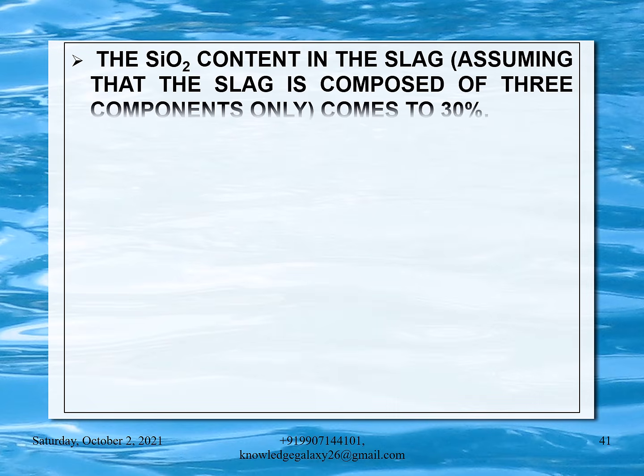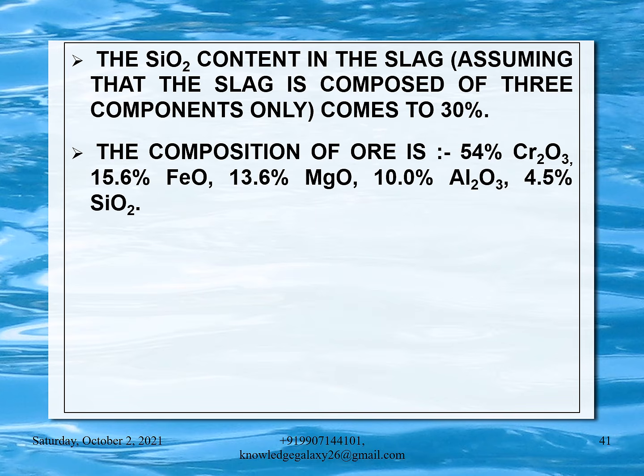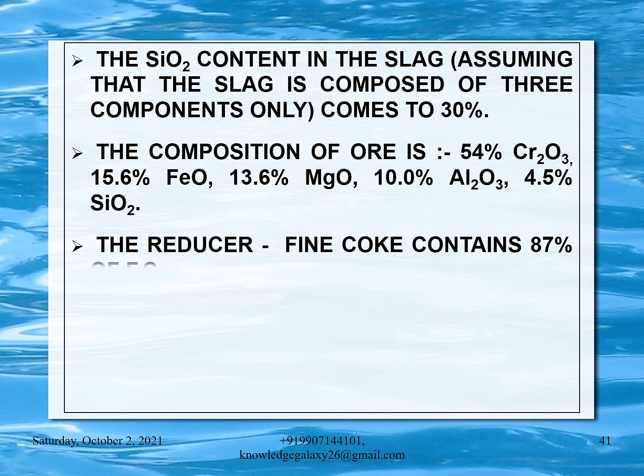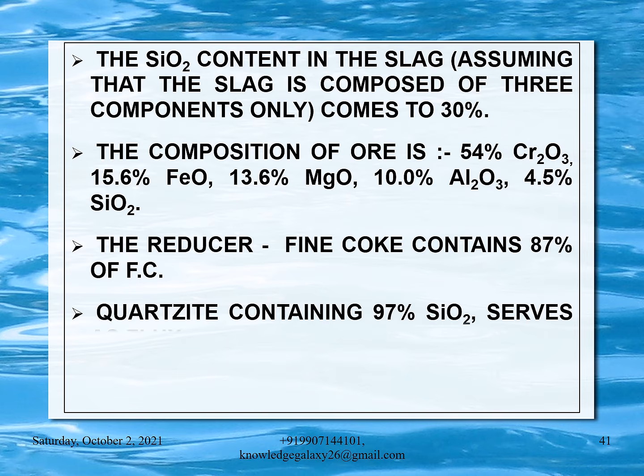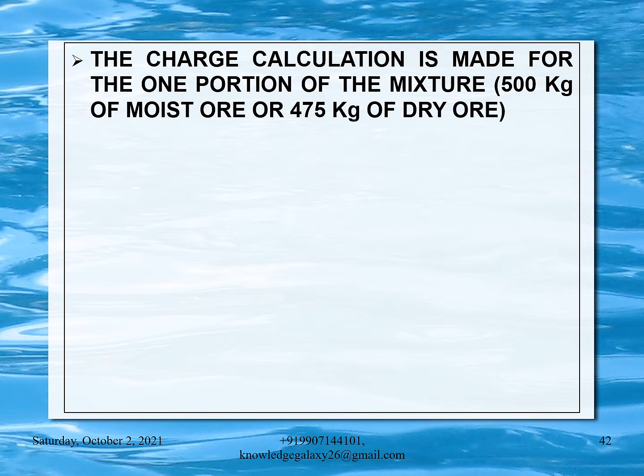The SiO2 content in the slag, assuming that the slag is composed of 3 components only, comes to 30%. The composition of ore is 54% Cr2O3, 15.6% FeO, 13.6% MgO, 10% Al2O3, 4.5% SiO2. The reducer fine coke contains minimum 87% of fixed carbon. Quartzite containing 97% minimum SiO2 serves as flux. The charge calculation is made for one portion of the mixture, that is 500 kg of moist ore or 475 kg of dry ore.